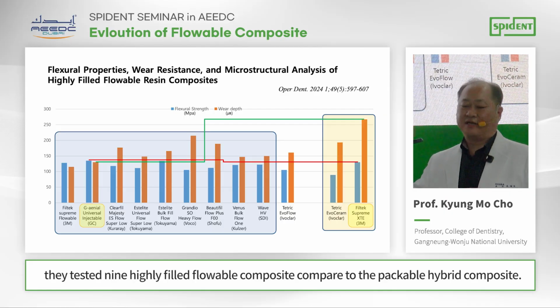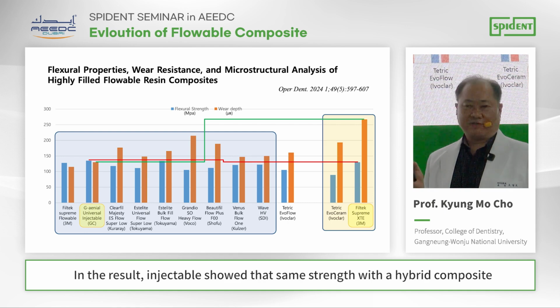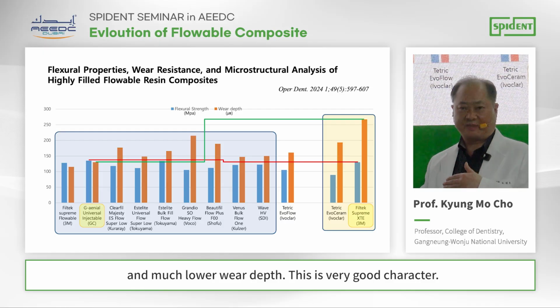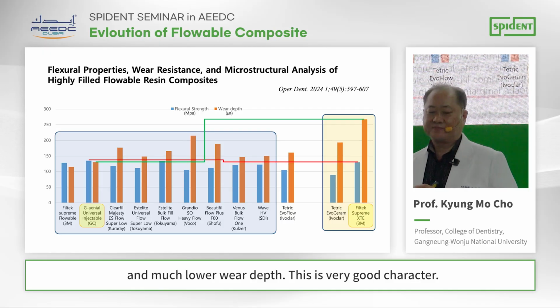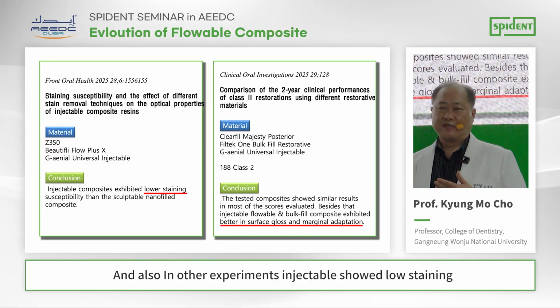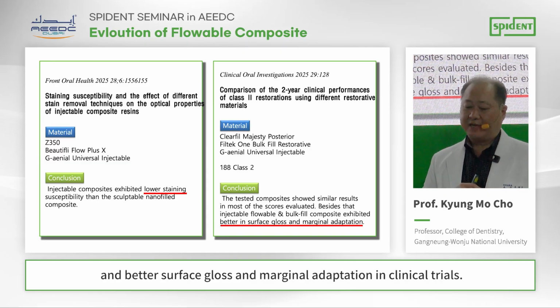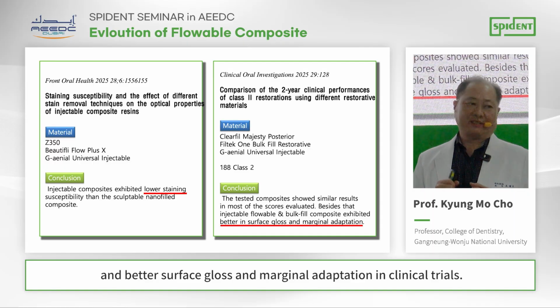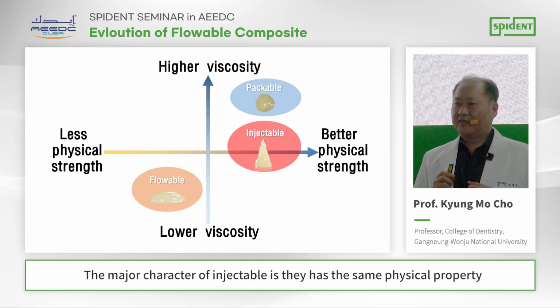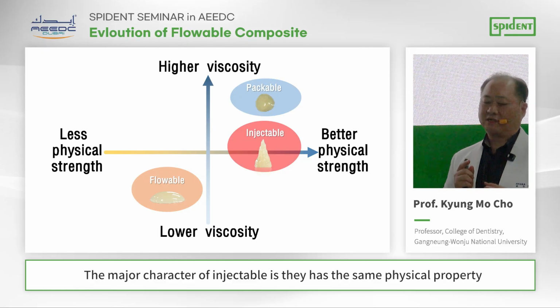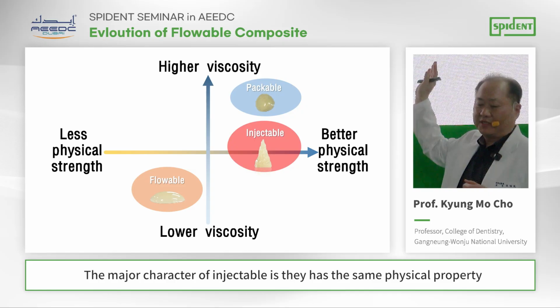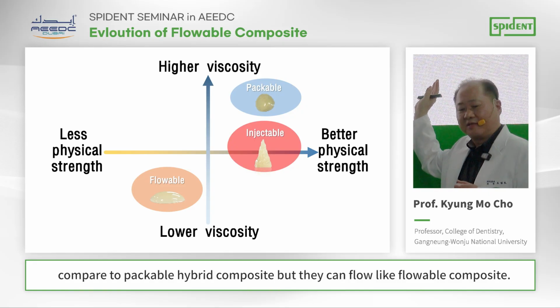In this study, they tested nine highly filled flowable composites and compared them to the packable hybrid composite. In the result, the Injectable showed the same strength as the hybrid composite and much lower wear depth. So a very good characteristic. And also in other experiments, Injectable showed lower staining and better surface gloss and marginal adaptation in clinical trials. The major characteristic of Injectable is that it has the same physical properties as the packable hybrid composite, but it can flow like a flowable composite.